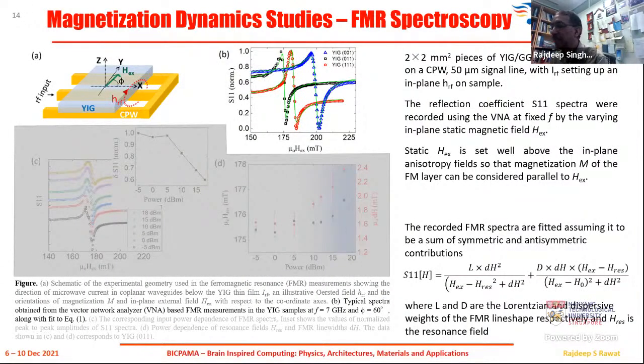Now, as far as the setup of this FMR spectroscopy is concerned, it is shown in figure A. When the RF current flows into this CPW, it generates the in-plane h_RF field, which makes the magnetization precess. Using the VNA, we capture the S11, which is the reflection coefficient, and those spectra are shown in this diagram. These spectra can be fitted with the formula listed here, which has L and D, the Lorentzian and dispersive weight factors. From there, you can find the resonance magnetic field as well as the line width ΔH. So those have been deduced.